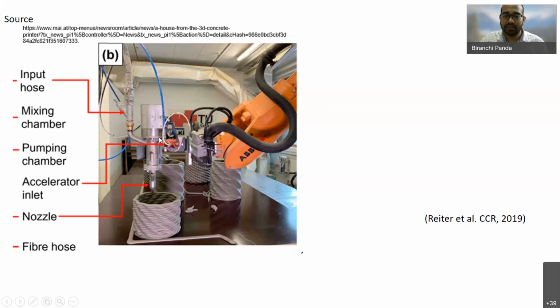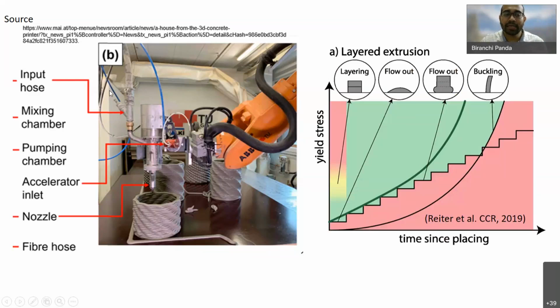So if you want to go with the second approach, you have to add some chemicals which are going to reduce the setting time of concrete. Setting time means the time that is needed to get hardened. So if you want to play with the setting time of concrete and add more chemicals, we have to come up with a nozzle design concept where one inlet will be used for material and another inlet will be used for the chemical, and these two get mixed and deposited layer by layer, so that once you deposit the material, it will immediately get hardened, and as a result you can print more layers without any deformation.